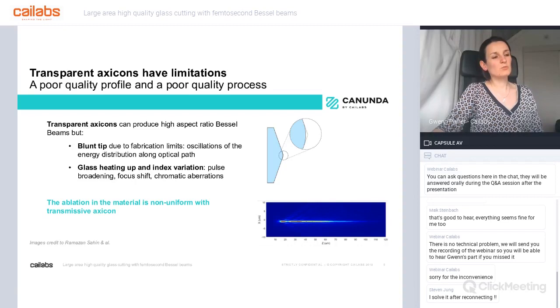So why is it actually pretty bad? It means that either you will be below the ablation threshold somehow in some areas, and you will not ablate the glass. Or you will be above the ablation threshold everywhere, but where you have the high intensity, you will be too much above this threshold, and you may create damage in the glass. So that's actually one big drawback.